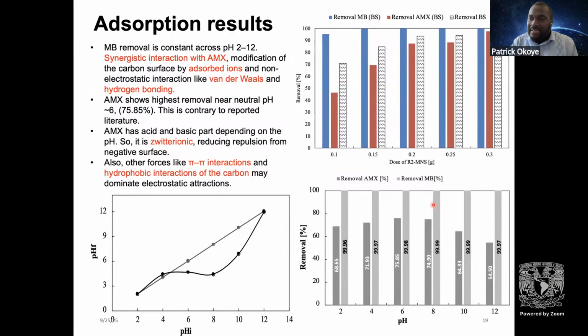And what is the cause of this? Why are we having an unexpected behavior for this removal? It is because there is some interaction of these two pollutants. It shows that pollutants in the water interact with each other. And many times when the pH is elevated or reduced, there is some modification of even the adsorbent that you want to use. Hence, there are non-electrostatic interactions like van der Waals or hydrogen forces.